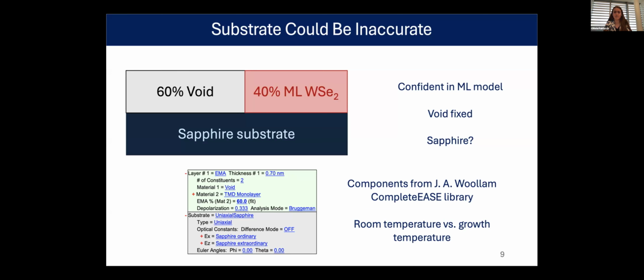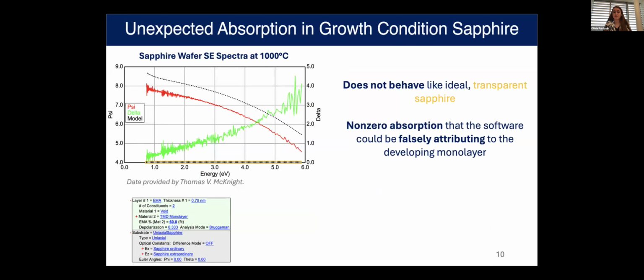So what does the sapphire actually look like? We have some data of sapphire SE at growth temperature, where we see that the model I had been using are those black and white dotted lines. And I've highlighted the one that should be modeling delta, that one in that kind of orange color, where we would expect for it to be transparent, that it should be completely zero. Delta is representative of absorption. So what we're seeing with that green delta data is that there is a non-zero absorption at that high end. So there's something that is being absorbed and not being counted by the software as the sample when it is perhaps from the substrate.